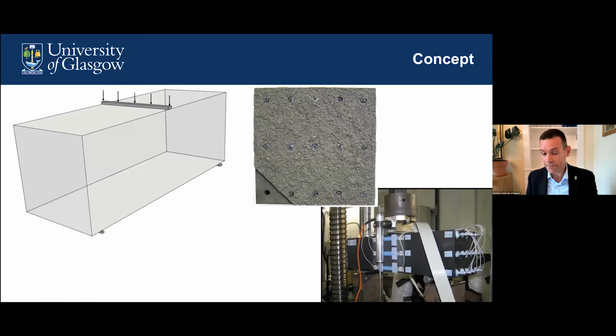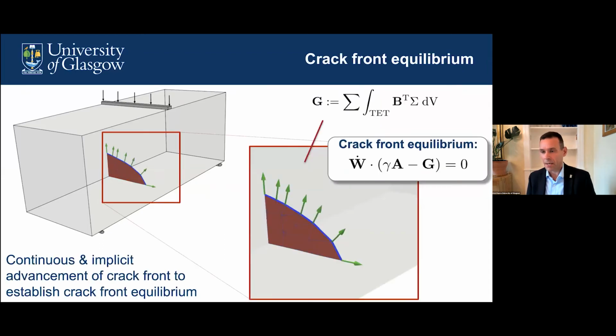So that's basically the essential framework. And then just very briefly, I'll show you how that works in practice. Here we've taken simply a 3-point bending test on a simply supported beam with an initial notch. And then what we're doing is just advancing the analysis. So the green arrows here are the so-called configurational forces. They are driving the crack propagation. The blue line is the crack front and the red is the crack surfaces.